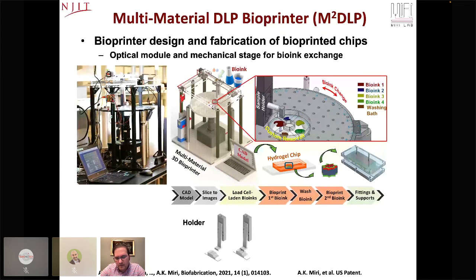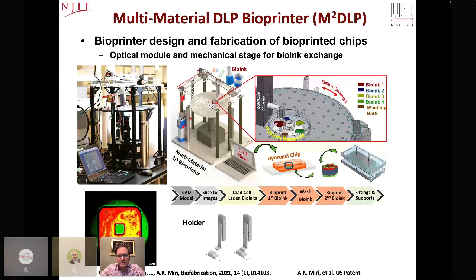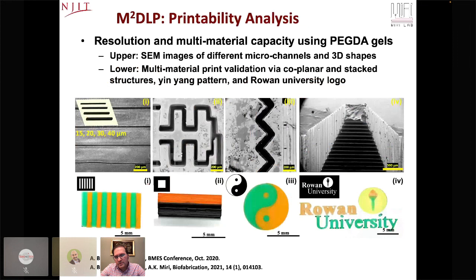Again, you can always have the concept of multi-material, just as an example here, because this is something you can imagine from a digital micromirror device in the system. When you develop the system, which I'm not showing all the details of, one of the first things we do is characterization, and the characterization starts with printability. In our case, we wanted a multi-material bioprinter, so we also have to check the printability for composites. The resolution was checked, as you can see, using PEGDA, polyethylene glycol diacrylate, at reasonable concentrations between 40% and 60% PEGDA.